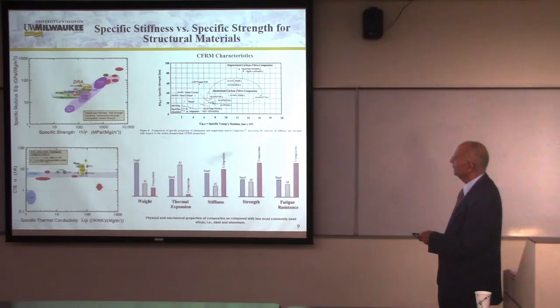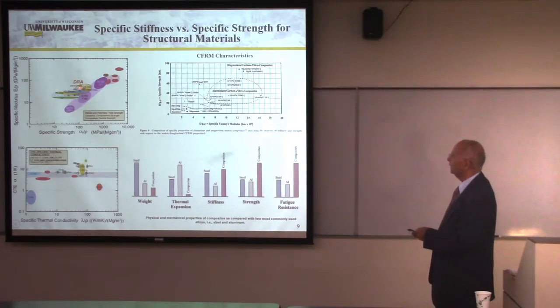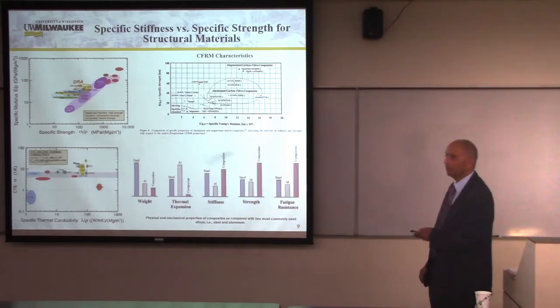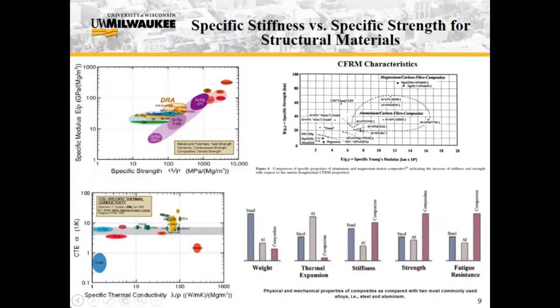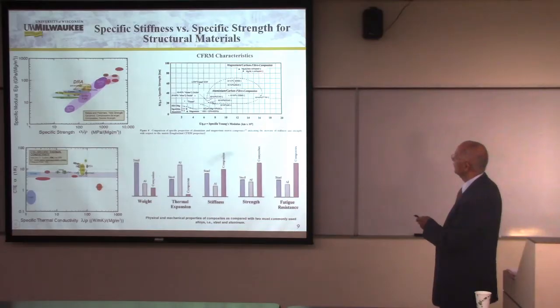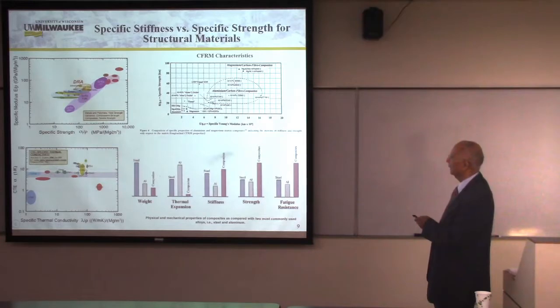And that is why the higher the combination of specific modulus and specific strength, the lighter can be the part for same stress application. This is why our transportation systems, cars, trucks, bicycles, motorcycles, scooters, and trains can be made much lighter if they have metal matrix composite components. And this is a similar plot of specific strength and specific Young's modulus showing that monolithic aluminum alloys are here, the composites are here, and if instead of aluminum you use magnesium as a matrix, you move along this line, that means parts can be made lighter and lighter.